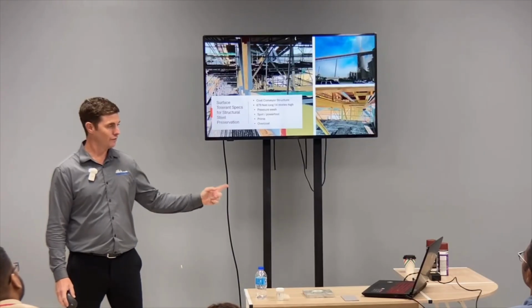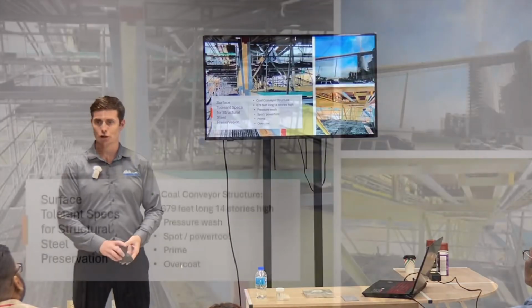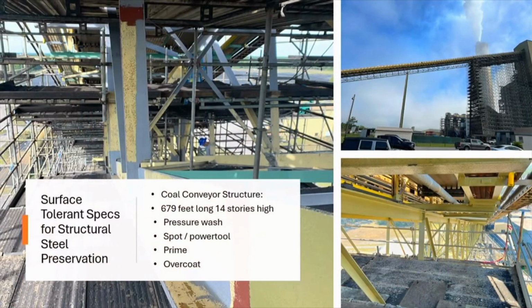This is a coal conveyor. So a very large structure. We did this as a nested contractor over the course of 3 years, taking a bite at a time, working in consistency with the on-site scaffolding contractor. This was a situation where we did what we call a spot prime overcoat. So you pressure wash the surface to reveal any weak areas and clean it. The areas that show corrosion or maybe blisters, you use power tools.